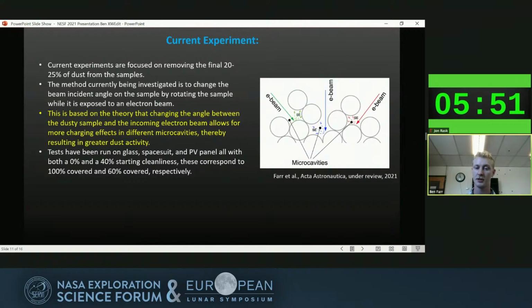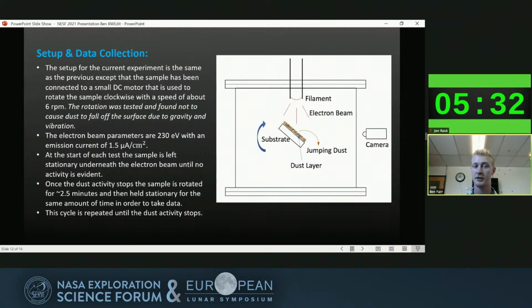And we were hoping that to get rid of that last 20%, we can rotate the sample relative to the beam source, which would change the angle between the beam and the dust. The idea is that this allows different microcavities to be exposed to the electron beam, allowing us to clean off more dust. We did some preliminary experiments, just rotating the sample without a beam, to show that no dust falls off just based on the rotation, the vibrations, and gravity, and nothing fell off, so that's good. So we're confident that any increase in cleanliness is just because of the changing angle.